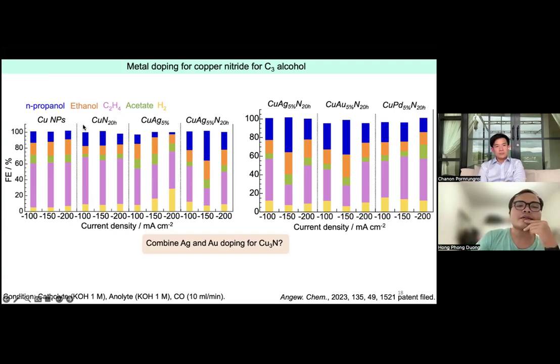And you see that, let's try, how about making nitrogen doping into this without any metal doping? We had a slight improvement in terms of n-propanol here, just a few percent. In the case of solely metal doping, you get much less n-propanol, which is quite unexpected, but it is a result anyway. But the important point is that when we combine the nitrogen and the metal doping all together, the efficiency for n-propanol was significantly improved, up to 30% at this current density, 150 milliampere per square centimeter.